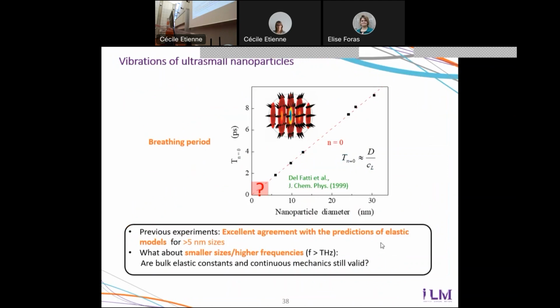So let's go back to spheres. With spheres, as I said, we detect one vibrational mode whose period is proportional to the diameter. And in the previous experiments, we had this proportionality between the period and the diameter. It was observed down to near 6 nanometer diameter. And of course, a goal at this time was to look at what happens for smaller nanoparticles, with the question: can one still describe the vibrations of very small nanoparticles of only 1 or 2 nanometer diameter with a continuum model?